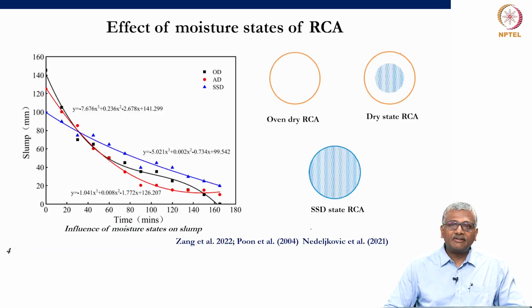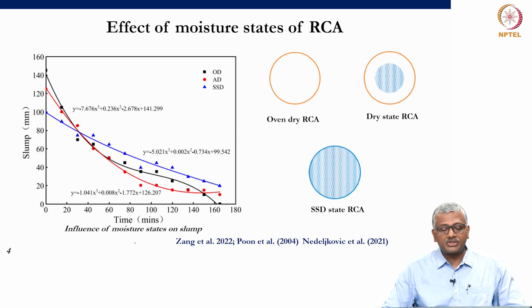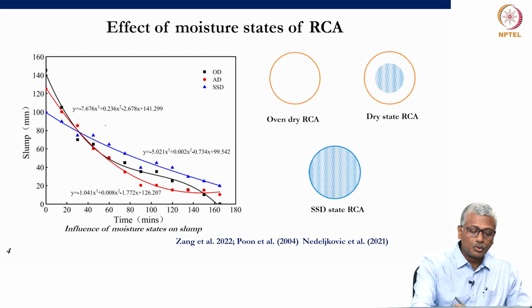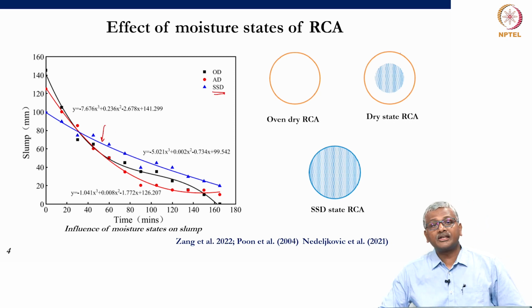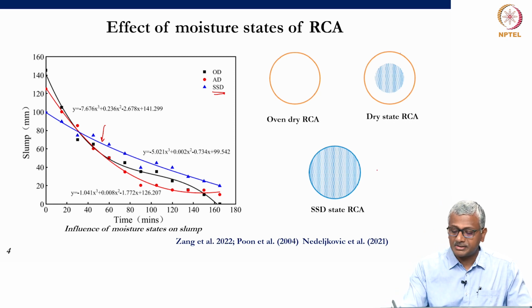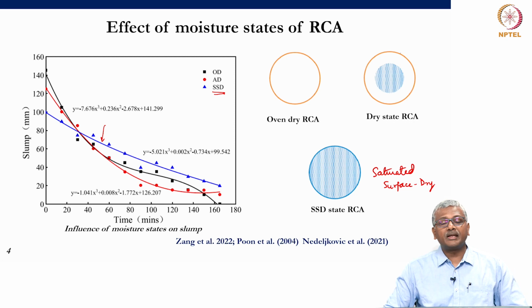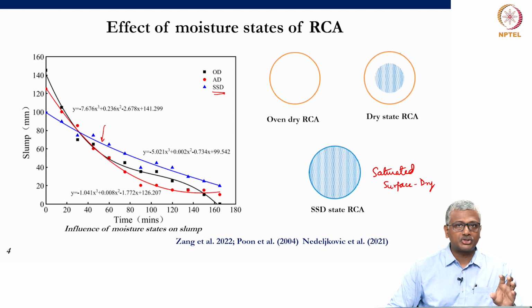So, just to show you the effect of the moisture states of RCA, this is one of the studies conducted by a few researchers. Here what it says is, depending on the moisture state, the slump loss with respect to time can change. For instance, if you look at this blue curve, which indicates the aggregates were in saturated surface dry condition. SSD means saturated surface dry. What does that mean? That means that all the accessible pores in the aggregate are saturated with moisture, but there is no extra moisture clinging onto the surface. So, that means SSD, saturated surface dry.